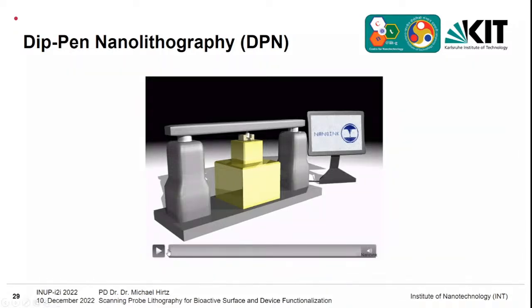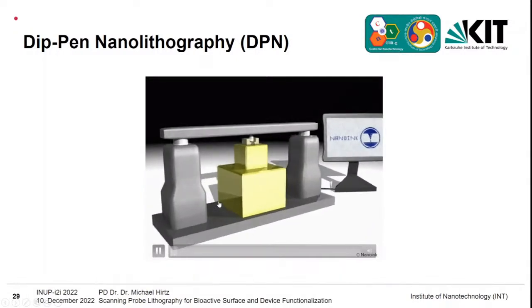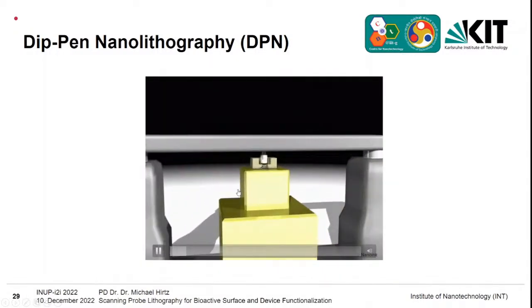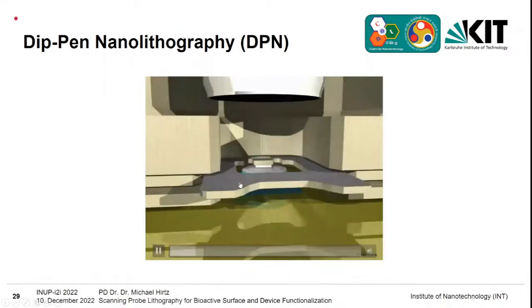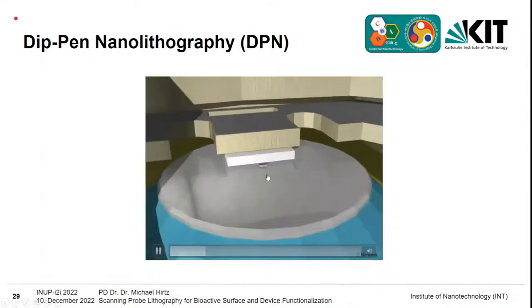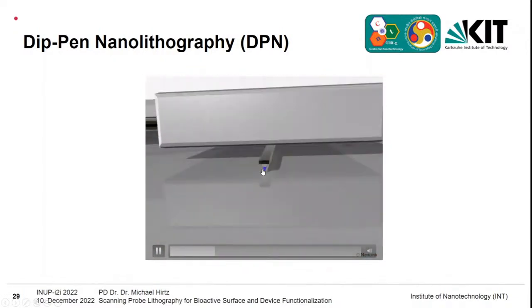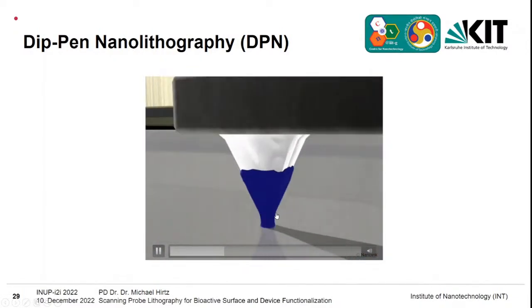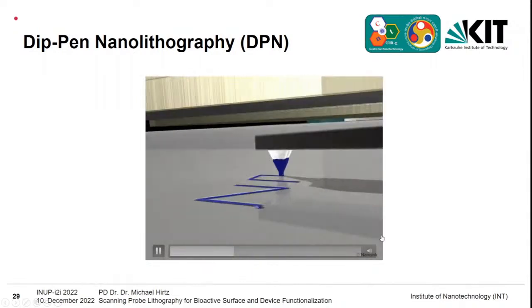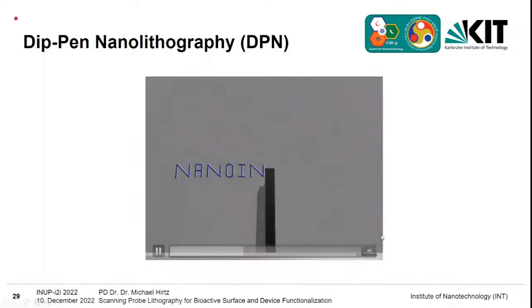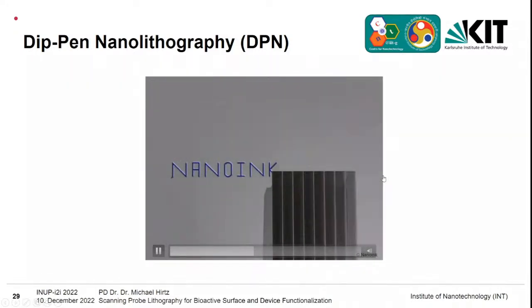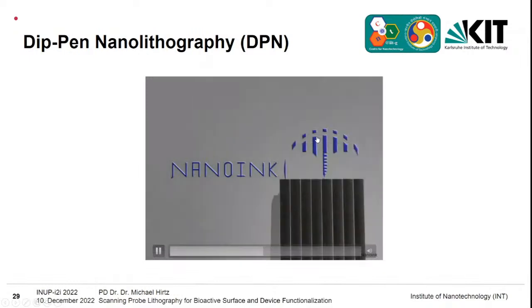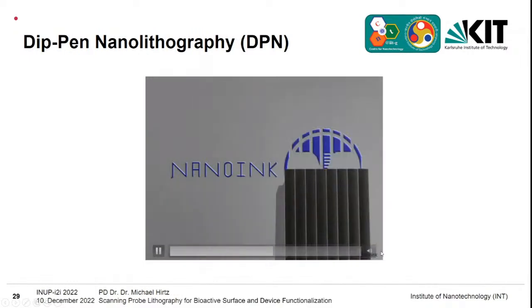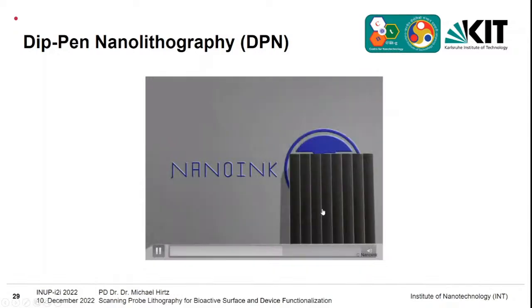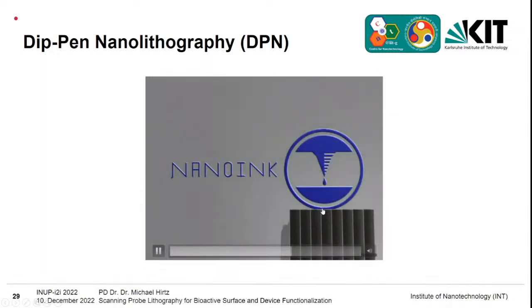Let me start this. So what you see here is now how that can be exploited. We zoom in on the AFM stage. And here you see the AFM tip, cantilever tip, and the tip is now covered, for example, with a thiol. And if you bring it to the surface, you can now write onto the surface really like you would write with a feather quill, let's say. This can also be parallelized again. So you can write different patterns with different tips in parallel to speed everything up. And now the whole image is transferring to a real AFM image.